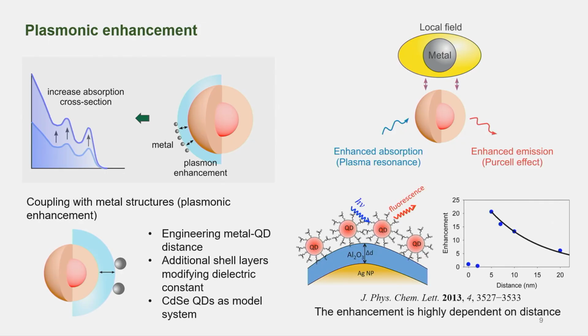In this approach, the distance is very, very important for the system, because if you get too close, you might see carrier transfer or carrier hopping from the quantum dots to the metal and really quench your emission. So in this case, we believe we need some spacer between the quantum dot and the metal structures. This spacer helps us engineer the distance between them, and it also modifies the dielectric constant of the surrounding medium. If we are careful and choose a dielectric constant shell between the air and the quantum dots, you can effectively see it as a coupling system, so that you can also couple light efficiently.